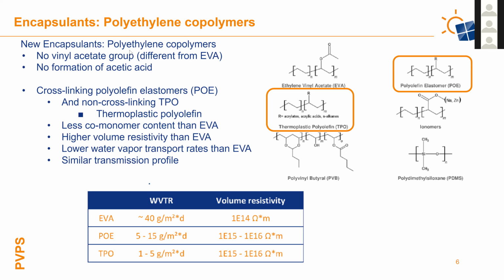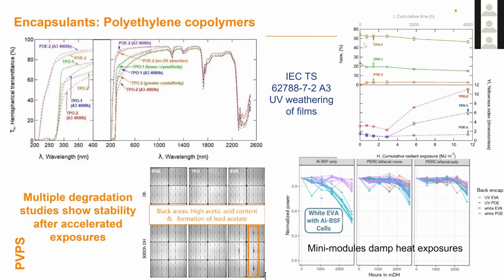This top figure shows POE materials at baseline and then at 4,000 hours. On this UV edge, we start getting loss of UV transmission from the different materials. POE2 drops slightly, TPO1 drops a lot. TPO2 has a much higher haze, generally due to much higher crystallinity, which would cause that higher haze value to start with. It has a reduction in haze over time, as well as TPO1, which suggests they are actually having a change in crystallinity during these exposures of irradiance. And they both slightly yellow, or TPO yellows much more than POE in these examples. So that's this top row of figures.